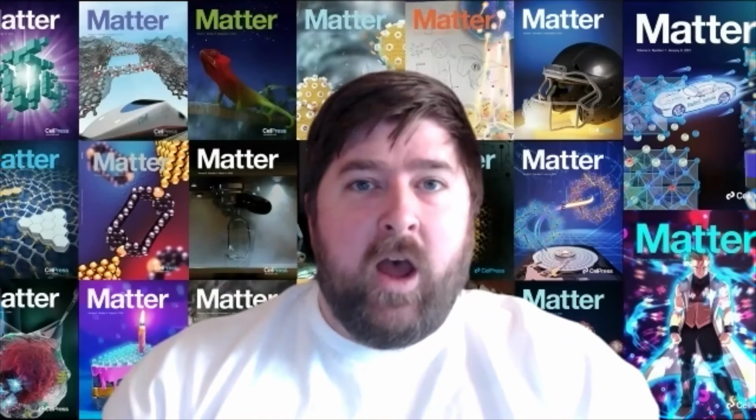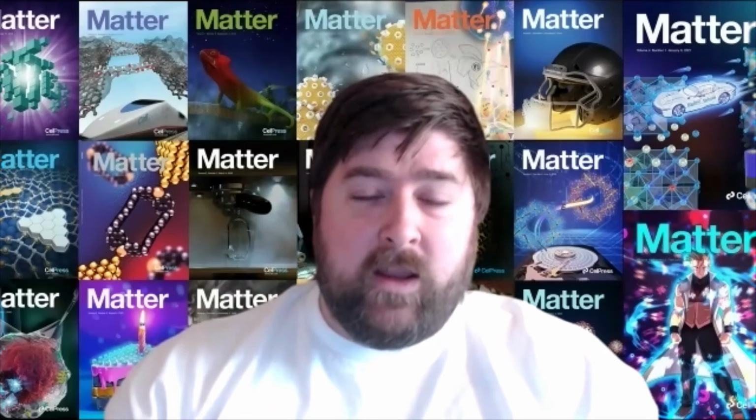The other component are longer strands of proteins that form amorphous zones. So you can think of spider silk as a composite material composed of these beta sheet crystals along with amorphous zones. Now the beta sheets give it strength, and the amorphous zones, when they get pulled, it's kind of like pulling spaghetti, they have to untangle and unfold, and that gives us some stretchiness. Also, when the beta sheets finally rupture, they unfold and give it even more stretchiness. So it's this combination and balance of the two that gives spider silk its ductility or extensibility or stretchiness.